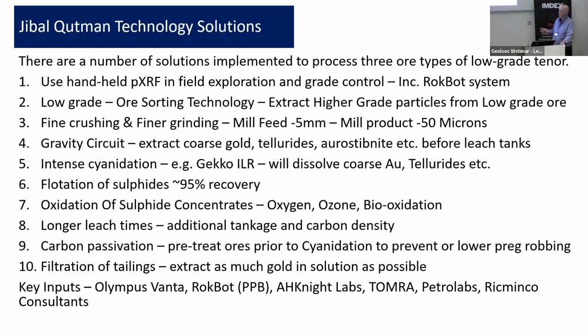Longer leach times. If you're doing a plant design, people will try and save capex on tankage. It's probably the most ridiculous saving of capex you could possibly imagine. The more tanks you have, the longer that dirt's in there exposed to cyanide, and the longer it's exposed to carbon to absorb the gold in solution. Carbon passivation treatment. We are looking at, there's a couple of tricks. I worked in Nevada for 5 years and I had an ore body of a similar nature. We developed a few processes to negate some of the carbon robbing characteristics of the ore. That's being reactivated in here.